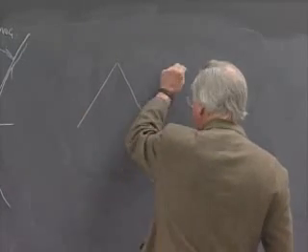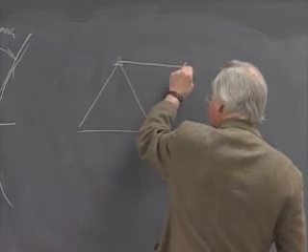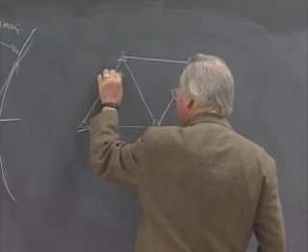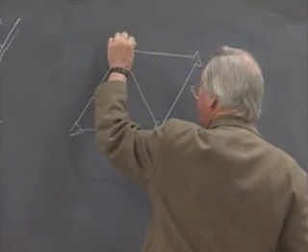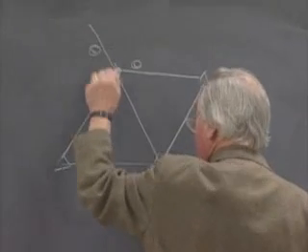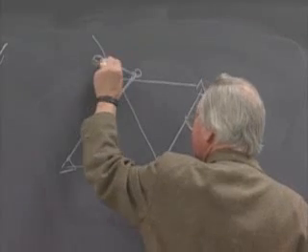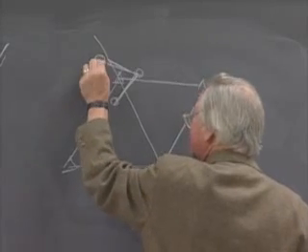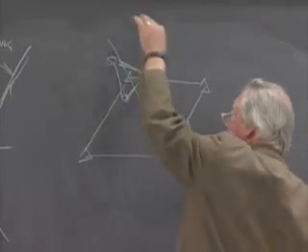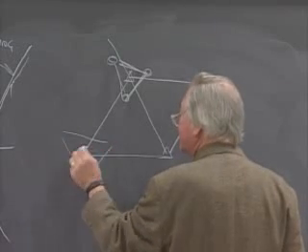The structure of selenium and tellurium is a hexagonal structure, and there are chain-like molecules that are pairs of bonds that rise up around a threefold screw axis. So this is two coordinated atoms, and the structure just spirals up in this triangular spiral around the threefold screw axis.